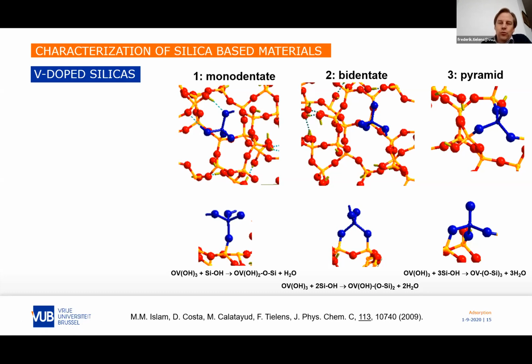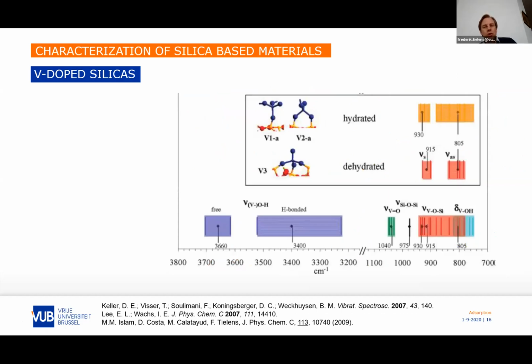From calculating these structures, we can build the thermodynamic phase diagram as we've seen before, and also some vibration frequencies. These structures are typically characterized by vibration spectroscopy, and in particular Raman, which shows a very precise band, green here, for the vanadyl bond, the V double bond O, oxygen. And the rest are in fact interactions with OH groups, which can be hydrogen bonded or free, and also the framework with the vanadium. These bands were determined with theory, with DFT, and compared with experiments.